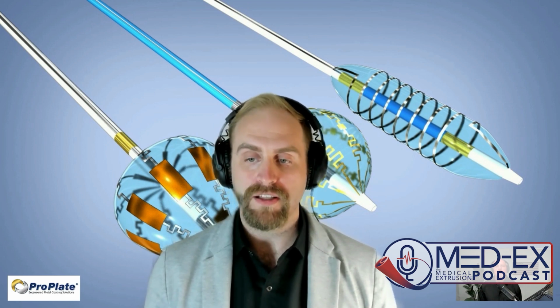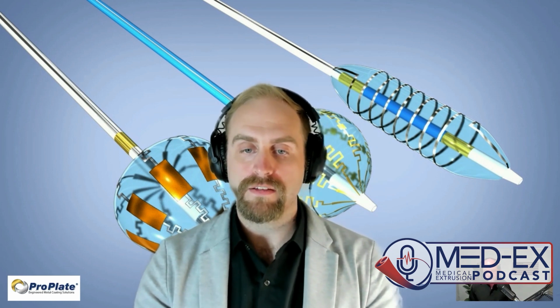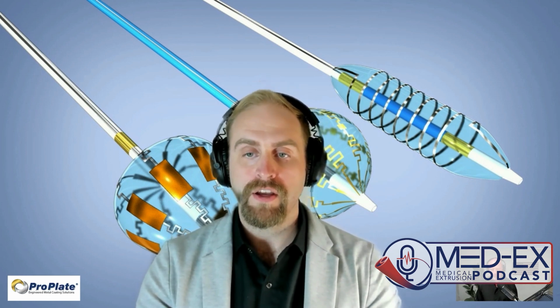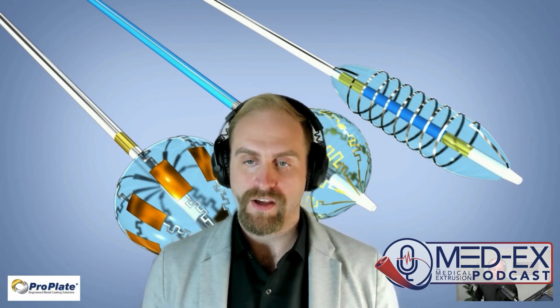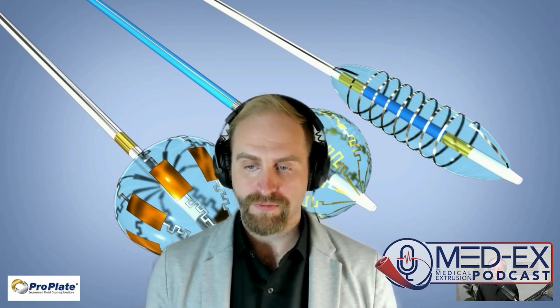And we explored electroplating methods to electrolessly plate, I guess, so not really electroplating, but plating methods to metallize catheters. But we found that, to your point, a lot of those chemistries will degrade catheters or the polymers, and it would require a lot of different chemistries, so a lot of floor print to have the right chemistry for every single polymer out there. Then we decided to explore the world of vacuum deposition, where we found a particular blend of vacuum deposition where we took some of our own learnings, could create thin film deposits on these 3D flexible polymer components for electrodes that would enable mapping, ablation, stimulation, and sensing.